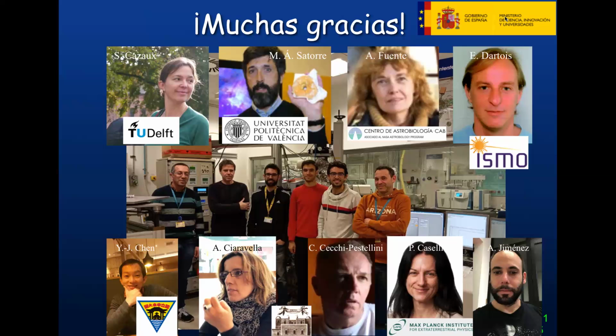Yeah. I have another very curious or technical question: how do you measure the temperature of the ice when you have such a small sample in a chamber? Yeah. We have silicon diode sensors on the surface where we grow the ice. So this is basically how we measure it, and then we compare when you warm up the ice. In the case of water, you see the desorption happening at a certain temperature, typically 170 K in the lab. So you see whether this temperature matches the one measured by other people in the lab, right? And we all tend to get the same temperature value. So that gives you confidence in what you are doing.